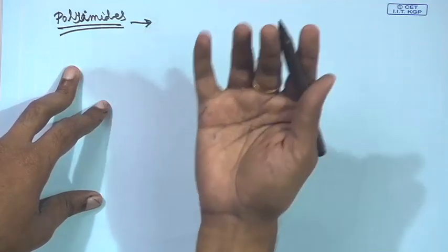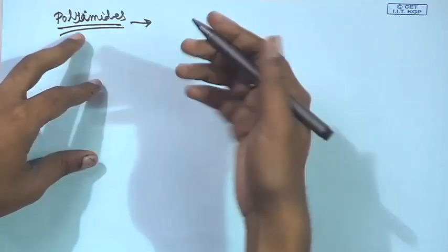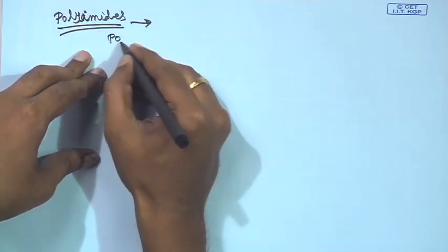Because even though you have made the polyamic acid and you have removed the solvent and you get the shape, you cannot mold them by conventional thermoplastic techniques, because if you heat it up, they do not simply melt. If you can introduce some thermoplastic property, for example, a little bit of flexibility at high temperature, that will help. So, commercially modified polyimides are used. A lot of modified polyimides are there, modification of polymer structure has been done. Some of the important ones, for example, are